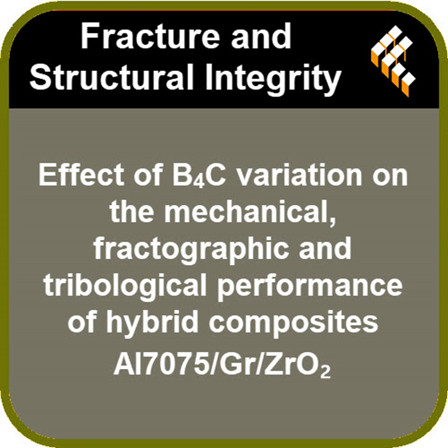But there's always a trade-off, isn't there? There is, and we have to address it. While it got dramatically stronger, the toughness did take a hit. Ductility decreased. How much of a decrease are we talking? Elongation dropped by about 14%. So from 14.2% down to 12.2%. Wait, a 14% drop? That sounds pretty notable.